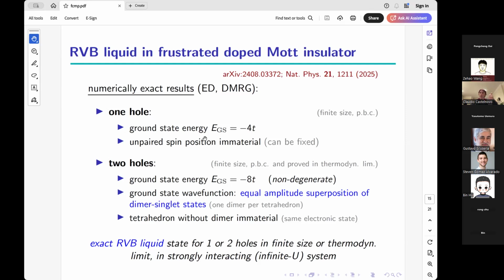Interestingly, if you put a hole in a finite-sized system, you necessarily have an unpaired electron, which therefore leaves behind an unpaired spin. And you would think that that could matter, but it turns out that it doesn't. It's perfect spin-charge separation, and the hole is unable to ever see this lone spin because of the same destructive interference effect that I mentioned earlier at the single tetrahedron level.